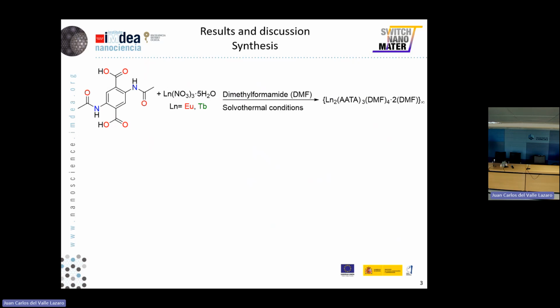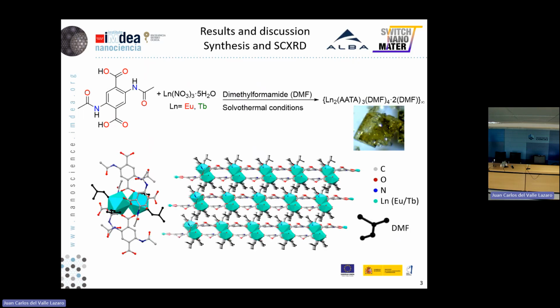After the selection of both compounds, we carried out the solvothermal synthesis of the materials, dissolving both compounds in dimethylformamide and putting them at high temperatures for several hours to obtain solvothermal conditions, which means we produce autogenous pressure, leading to the crystallization of the material. This material was chemically characterized in collaboration with the ALBA synchrotron, obtaining two-dimensional layers divided with DMF molecules and dinuclear clusters with 3 ligands and 4 DMF per cluster.